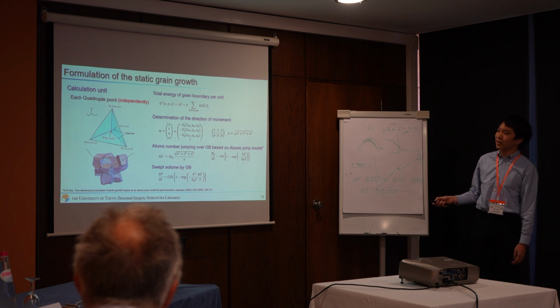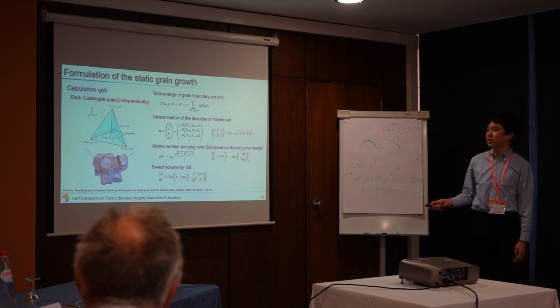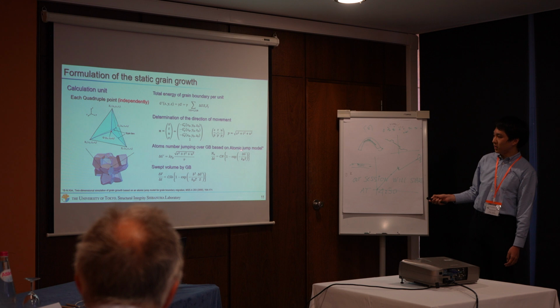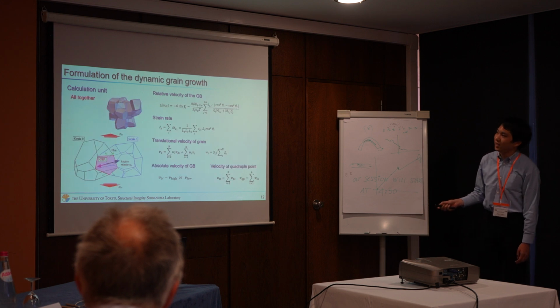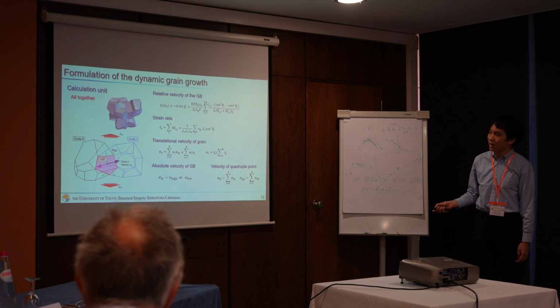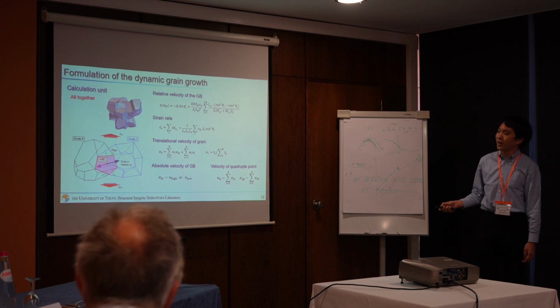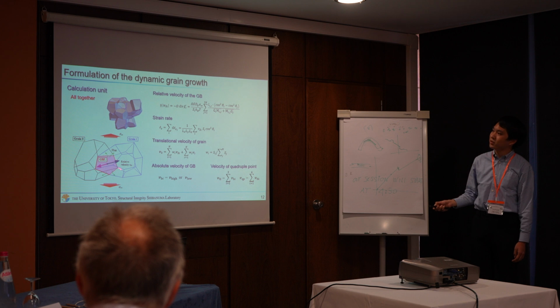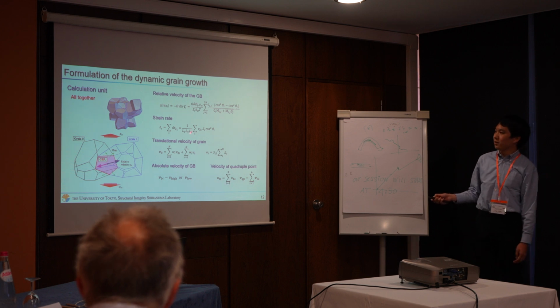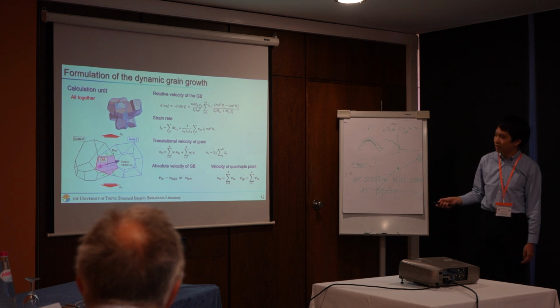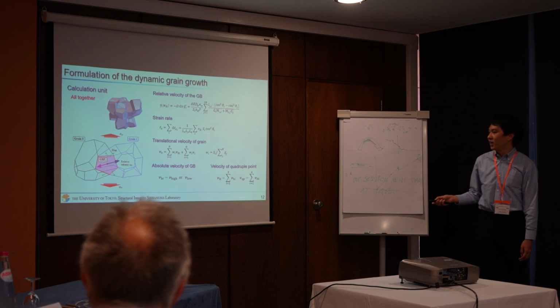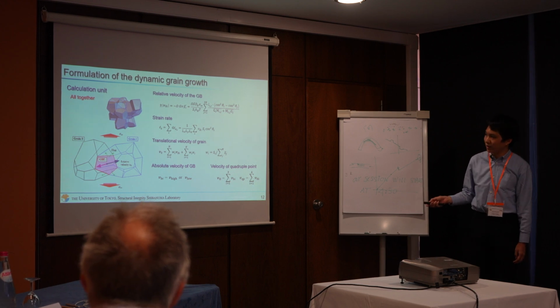So as to decrease the total grain boundary energy of this part, this unit, the velocity of each quadruple point is calculated based on the atomic jump model. And this is a dynamic grain growth formulation. Considering the diffusive flux of the grain boundary, the relative velocity of the grain boundary is calculated. Based on this velocity, the strain rate, translational velocity of the grain, and the velocity of the quadruple point are calculated.